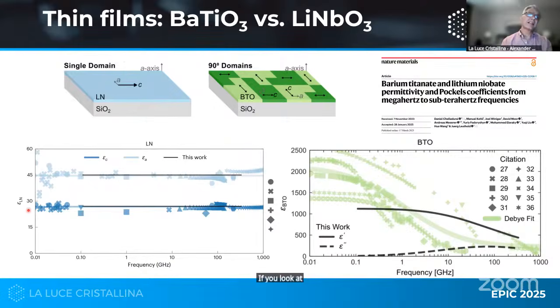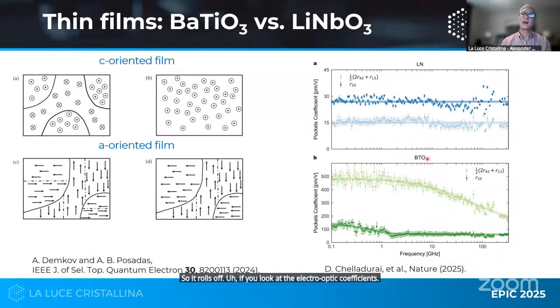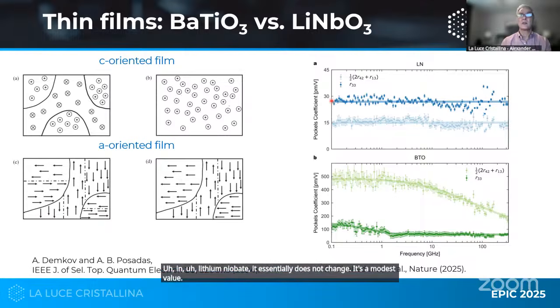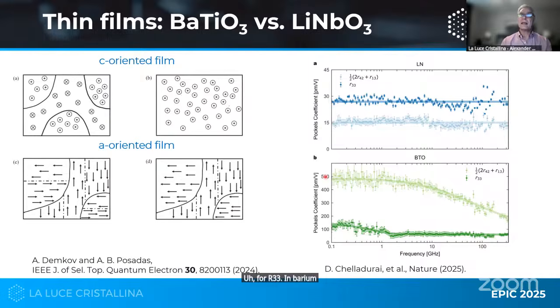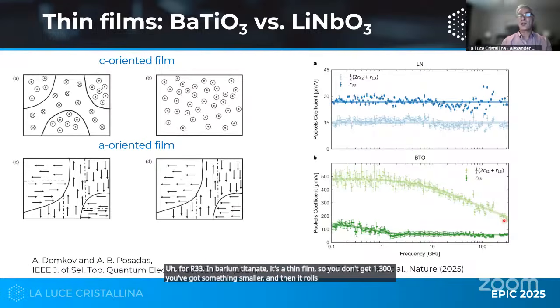If you look at the dielectric tensor in lithium niobate, it's extremely stable with frequency, no change. In barium titanate, there is change, so it rolls off. If you look at the electro-optic coefficient, it's quite the same thing. In lithium niobate, it essentially does not change. It's a modest value. It's in thin film. It's below 30 for R33. In barium titanate, it's a thin film, so you don't get 1,300. You get something smaller, and then it rolls off. But actually, it's still large. It's still over 200 when you go to very high frequency.